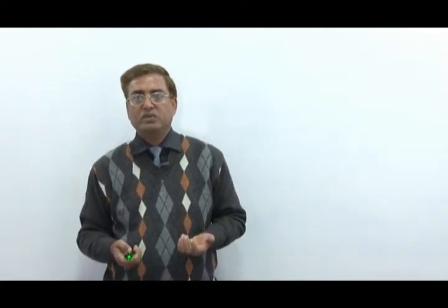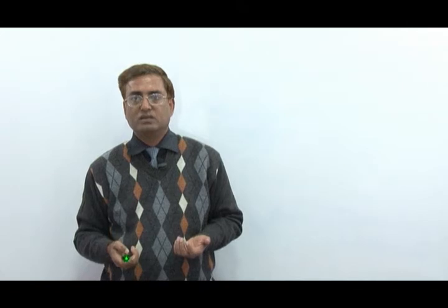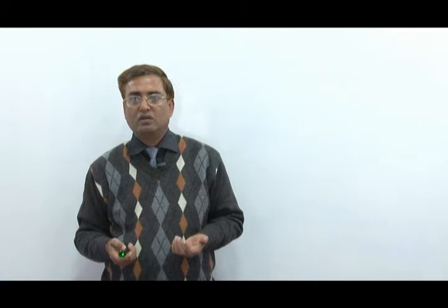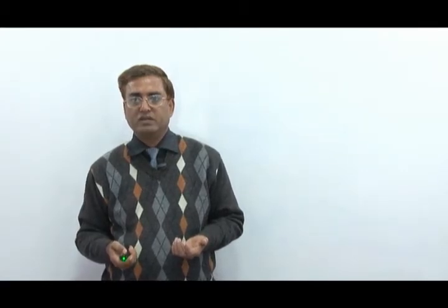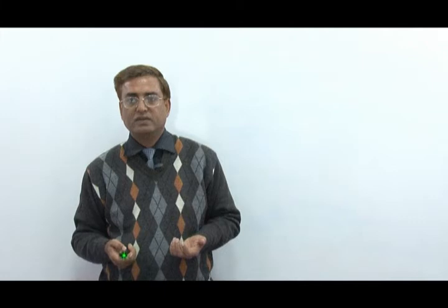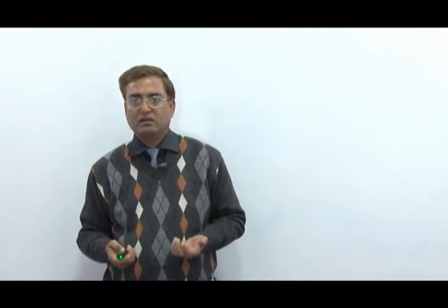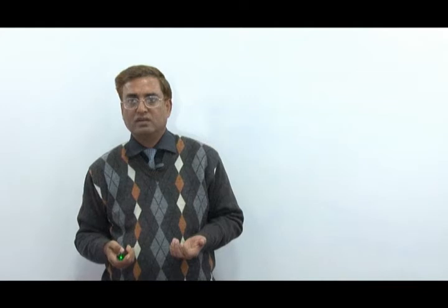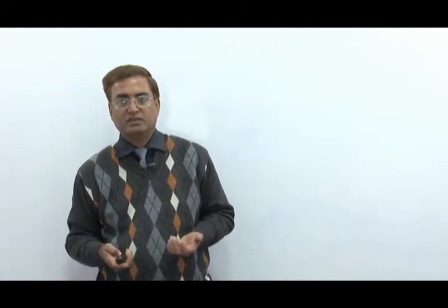Up to 0.6, there is a very drastic drop in the internal power of deformation and the discontinuity power, but on the other hand the frictional power increases as you increase the relative die length.